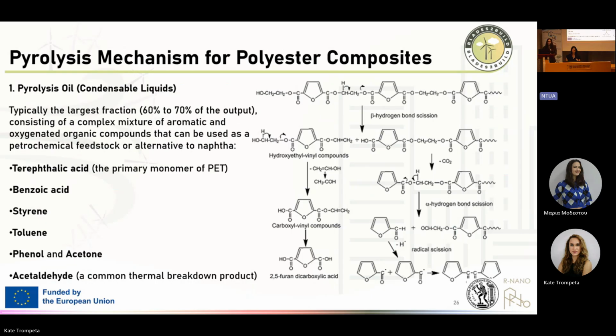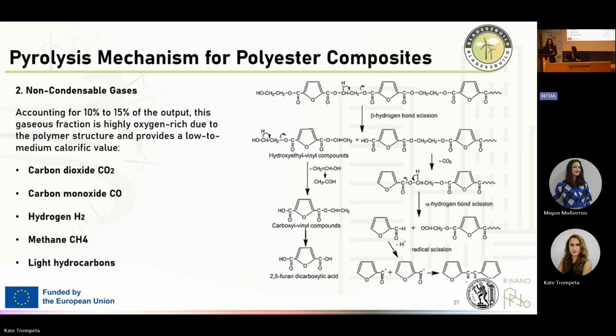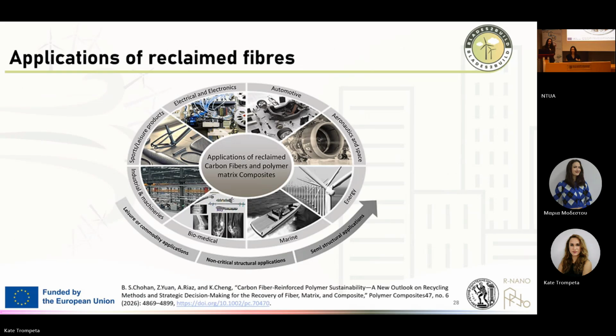The glass fiber reinforced polymers, as mentioned before, consist of polyester resin, which means that during the decomposition we have the primary monomer of PET, which is terephthalic acid, benzoic acid, styrene, toluene, phenol, and acetone, as well as acetaldehyde, which is a common thermal breakdown product, and also non-condensable gases that are released to the atmosphere, like carbon dioxide, carbon monoxide, methane, hydrogen, and some light hydrocarbons, which all means that these processes are not very eco-friendly in terms of the emissions that they produce. So our studies and research need to focus on the reduction of the emissions produced during these processes, and to find new ways for the recovery of the byproducts. So to conclude this part, we have fibers that can be recovered through this methodology, and this can be applied in different sectors.